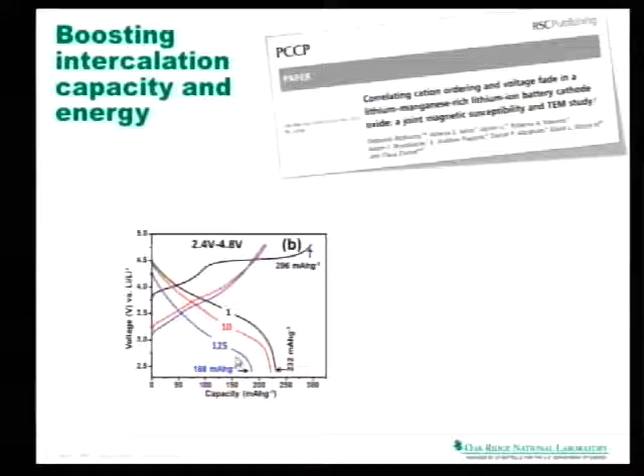But it shows two detrimental things. One is it reduces its capacity as you cycle it. That's capacity fade. That's something we have in the other materials too, and we slowly were able to solve them and to extend the lifetime. But something this material does is, see how this plateau of the discharge curve is slowly dropping and coming to a lower voltage. This is what we call voltage fade.